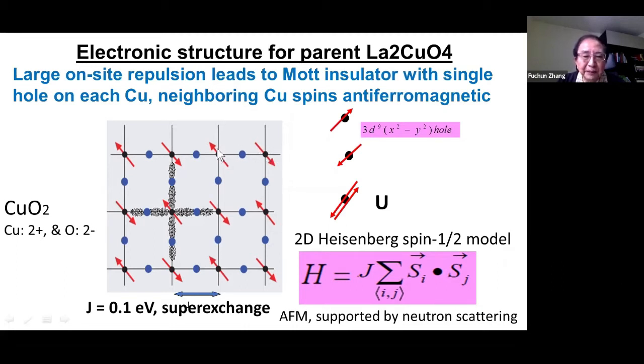And then the superexchange between the two neighboring holes will give us this J. It's antiferromagnetic, of the order of 0.1 eV. And so the model for the parent compound is well described by the Heisenberg model on a square lattice. The neutron experiment actually strongly confirms this. The system is antiferromagnetic, and the excitation spectrum is very much consistent with the Heisenberg model's result. So this is a spin-1/2 2D Heisenberg model.